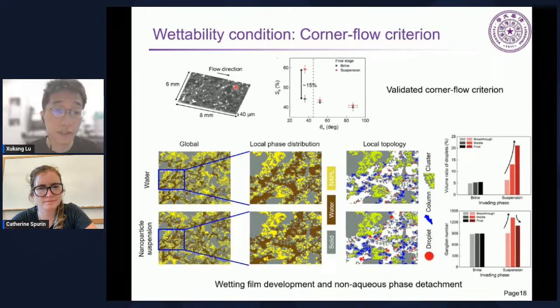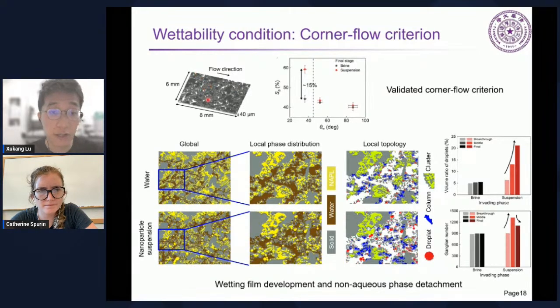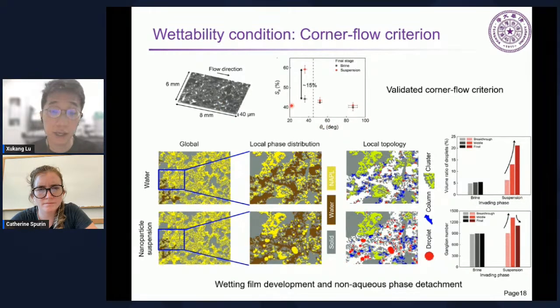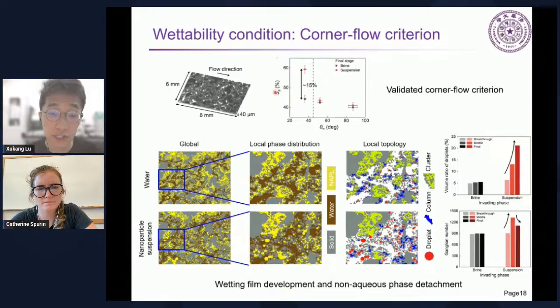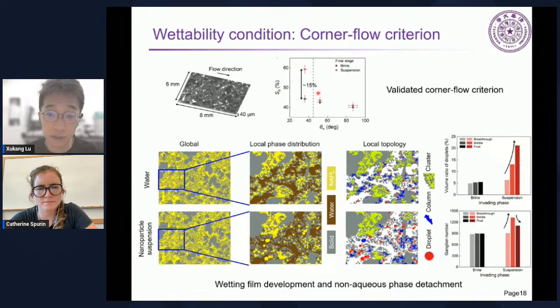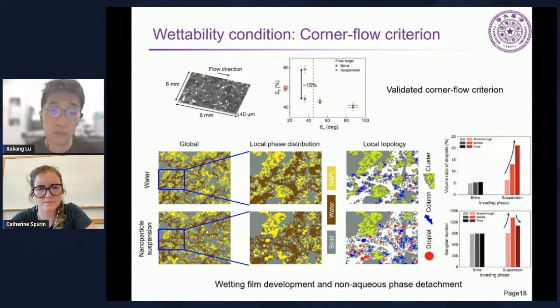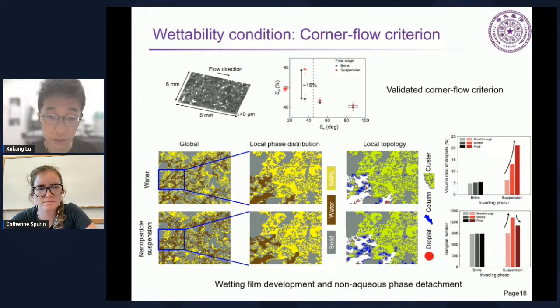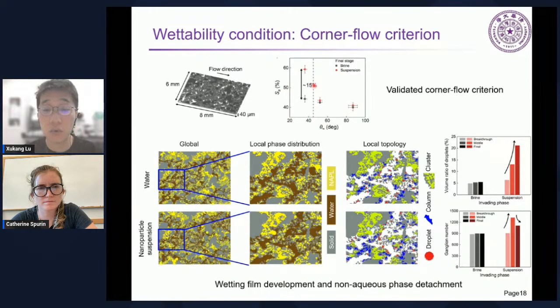So we start from this complex porous structure we constructed with a very precise distribution, and we change the substrate wettability and see how the aqueous phase saturation, SA, varies under different conditions. So it basically corresponds to the displacement efficiency. And it is very clear that only when the corner flow criterion is satisfied, when the surface is already a little bit hydrophilic, can the nanoparticles induce a strong increase in this aqueous phase saturation.